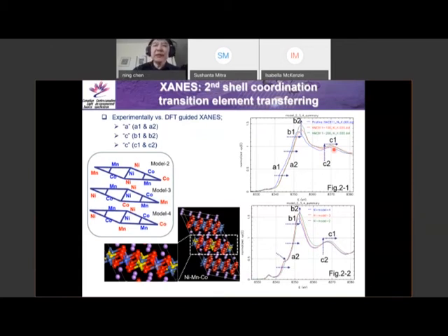So in this way, we have a DFT calculation. So we have a structure framework. And this DFT predicted that this is a lithium, this is a battery study. And then from here, we have lithium here. And then between the lithium kind of a plane embedded, we have this kind of structure. So this kind of structure here, we have three elements with a different partition ratio: nickel, manganese, and cobalt. And then here is the XANES spectrum. So what we have here, and then based on the DFT prediction, we can see that we have different configurations based on external stress, certainly.